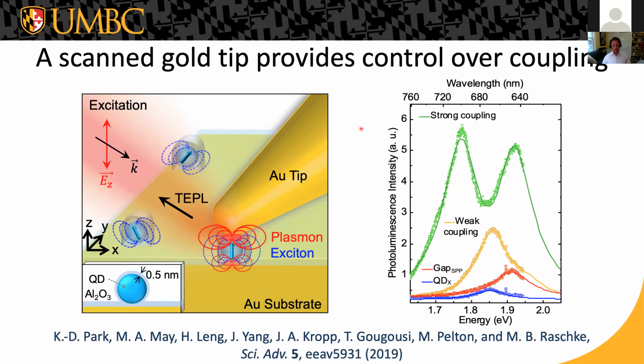So you can see that we go from just having the emission spectrum of the isolated quantum dot. When the tip comes nearby, the emission gets stronger. We're seeing the Purcell enhancement when we're still in the weak coupling regime. And when the tip is located right on top of the quantum dot, the photoluminescence spectrum splits into two clearly resolved peaks, bringing us solidly into the strong coupling regime. And now, like I said, we can do this over and over again. We can do this for one dot, move over to another dot, measure many dots this way.